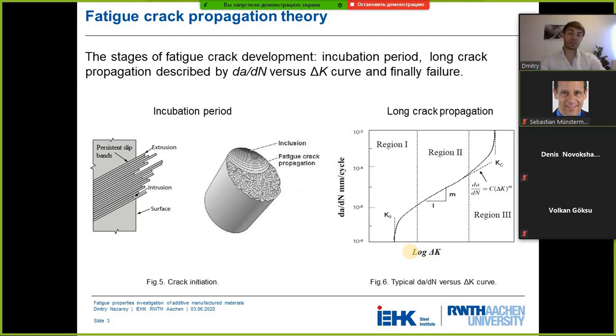I will also give some information about fatigue propagation theory. The crack propagation is comprised of an incubation period, which in my case was the time from the load application until the crack reached a length of 1 millimeter. The incubation period also comprises crack initiation. Normally the crack initiates from the surface, at inclusions or from cracks, but also slip bands could serve as an initiation point.